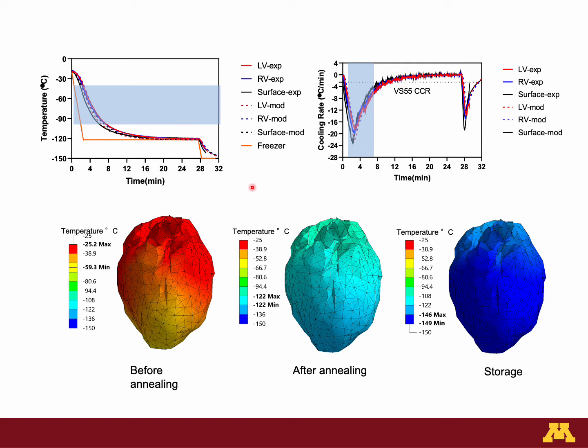To support these experimental thermometry observations, we performed finite element modeling to estimate the thermal behavior not only at the sites where the thermocouples were placed, but also throughout the heart. These are the color maps representing the temperature distribution of the heart during the cooling. You're looking at 3 states of cooling: before annealing, after annealing at minus 122 degrees Celsius, and close to equilibrium around minus 150 degrees Celsius, which is a storage temperature.